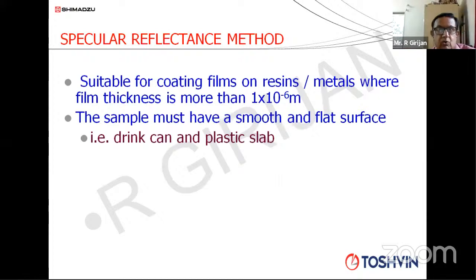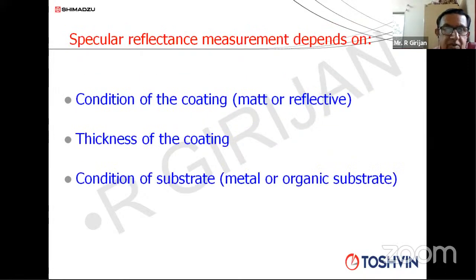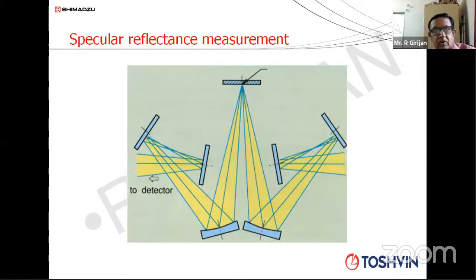Okay. Now, the specular reflectance method is suitable for coating thin films on metals, and the only requirement is that the thickness of the film should be more than 1 micron. That's all. And you can analyze different types of samples wherever there is a coating of a film on glass, or a coating of a film on a metal, provided the coating is more than 1 micron. And this is the attachment. This is called a specular reflectance measurement attachment.